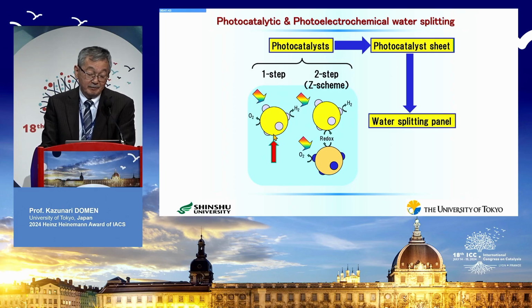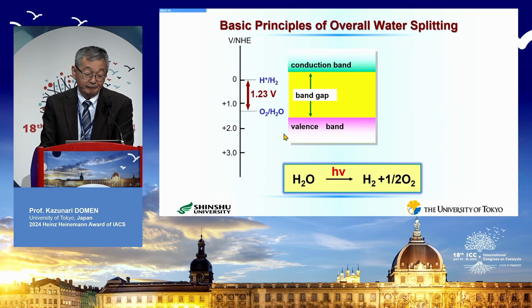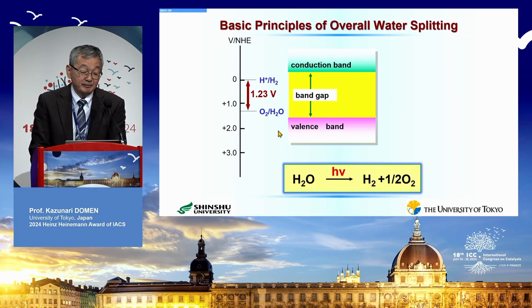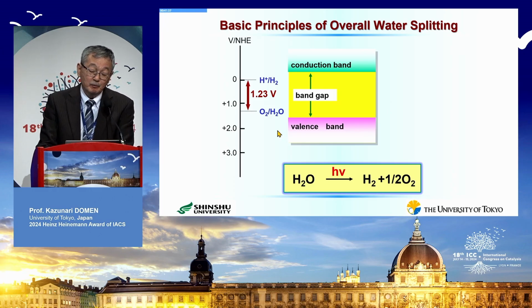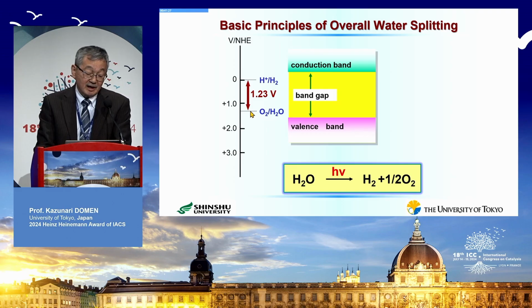However, probably this is the most difficult way to split water. Here I show the simplified basic principles of the one-step overall water splitting reaction. This is the normal hydrogen electrode at pH equals 0. Therefore, of course, the hydrogen evolution potential is located at 0 volt, and the thermodynamic oxygen evolution potential is located at plus 1.23 volt. This is the band gap position of a particulate photocatalyst referring to this axis.